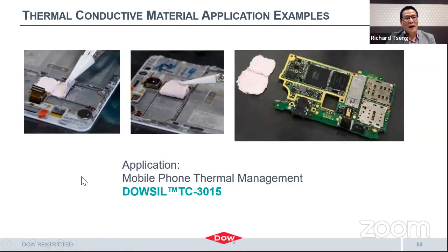Another example of gap filler applications in consumer electronics is the mobile phone. You can see the gap filler is used to conduct heat to the LCD chassis, which is die-cast aluminum. In this case, we use DOWSIL TC-3015 2 to cool down the key module ICs and dissipate heat to that chassis. In this case, it's quite successful. The customer is actually able to repair and remove the thermally conductive gap filler much more easily without any residues.